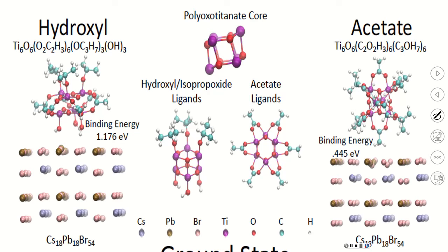This is not purely the creative credit of Landon. The idea of which ligands to use is known from experiment. In fact, the small clusters of titanium dioxide can be crystallized in a super array of these quantum dots, and the positions of each atom can be extracted by X-ray diffraction. So there are research groups who do it, and here credit goes to John Fogel, who looked through the literature and suggested which coordinates to use. So there are well-defined structures of bright titanium dioxide clusters.